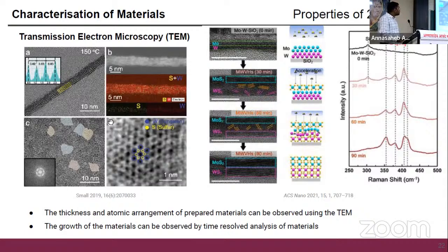If we also do a top view of these synthesized materials, we can find different phases present, for example the 1T phase or 2H phase region. Depending on the molecular arrangement, you get different fringes and different distances between the layers. Typically the 2H and 1T phases have different layer distances, so from that we can easily identify the molecular arrangement.